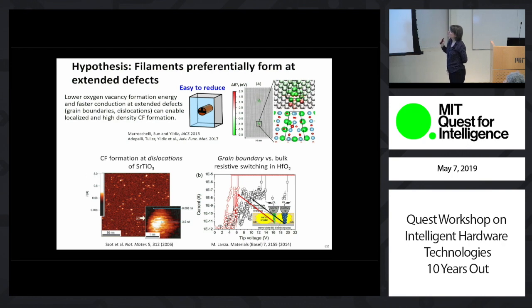So our hypothesis is that in oxides, the oxygen vacancy filaments, or accumulation of oxygen vacancies when you apply voltage or current, should preferentially take place along extended defects like grain boundaries or dislocations. And we know this from our theoretical work on both binary and ternary oxides. For example, here we are simulating strontium titanate and dislocations in strontium titanate. And the color code here represents the vacancy formation energy, green being lower and red being higher than bulk nominal. So around the core, there are sites where you can remove oxygen and create oxygen vacancies more easily. Okay? And this is consistent with the under-coordination of oxygen atoms along those extended defects.